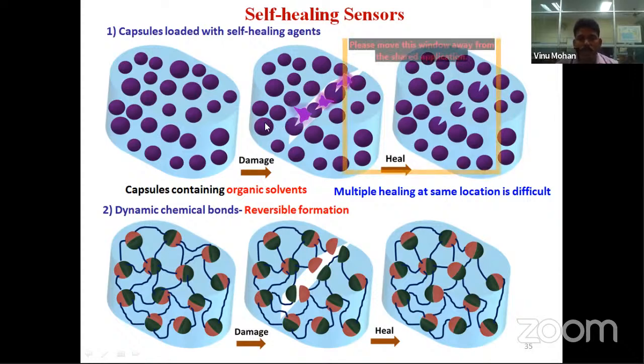So we have to use a very low concentration of these capsules, and it should be at the micro level. Only then can we have a homogeneous distribution of these capsules, and these releasing agents can self-heal the sensor by itself. But one problem with this approach is we cannot have multiple healing at the same location.